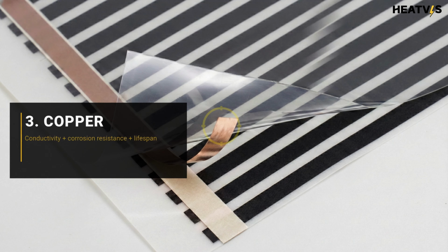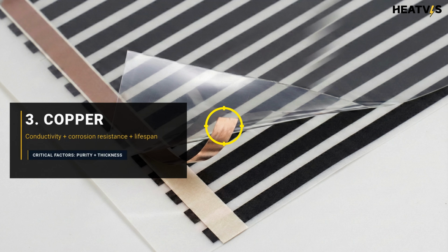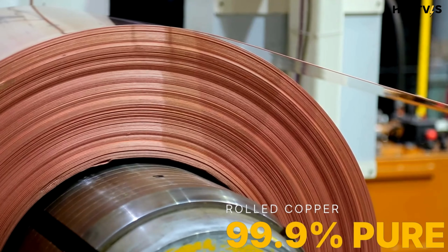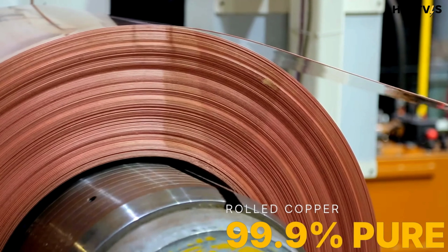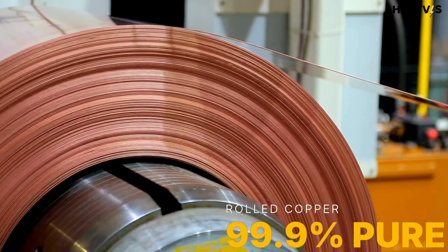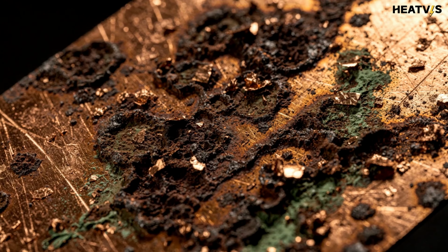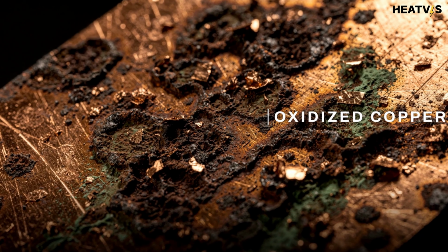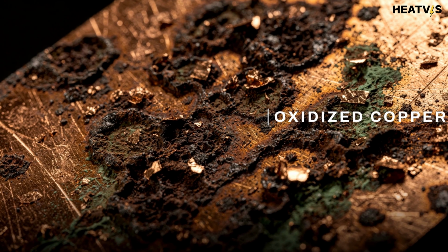Third is the copper electrode, the main pathway that delivers power across the film. Here, the most important factors are purity and thickness. High-quality film typically uses rolled copper foil with 99.9% plus purity, offering high conductivity and better corrosion resistance. Low-quality film may use lower purity or thinner copper that oxidizes more easily.